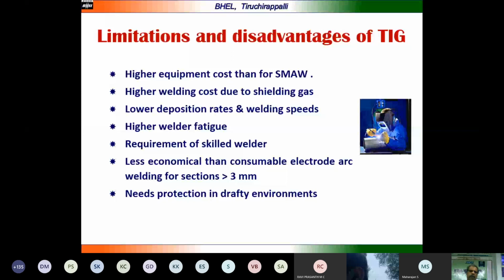Higher welder fatigue, because the hand-eye coordination of the welder is very critical for this process. The welder has to hold the torch in one hand, and if filler wire is added, he has to hold the filler in the other hand, then manipulate the welding. It requires highly skilled welders, and it is less economical than consumable electrode arc welding for sections more than 3 mm. That is why the usage is restricted to root pass welding, or at worst the hot pass over the root pass welding.